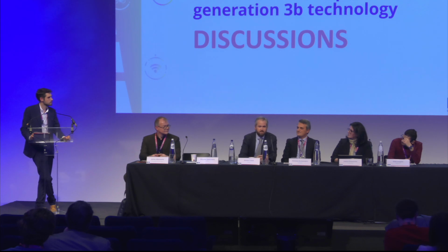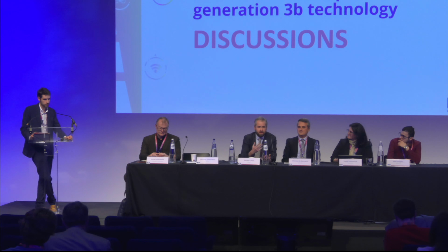Yeah, thank you. It's a good question. Long story short, it's extremely difficult. But there's a variety of ways that you can address it. It starts with your manufacturing techniques: anytime you're blending two materials, trying to get a good dispersion of those two materials so that you avoid conglomerates, especially in the case of silicon, where the big problem is swelling and it just ripping itself apart. So you can get some improvements with good dispersion and good manufacturing properties. You can also start looking into binders, ways to try to counteract the swelling of silicon to hold it together. But it's a very difficult aspect, and I think probably the most challenging aspect of developing these kinds of batteries.